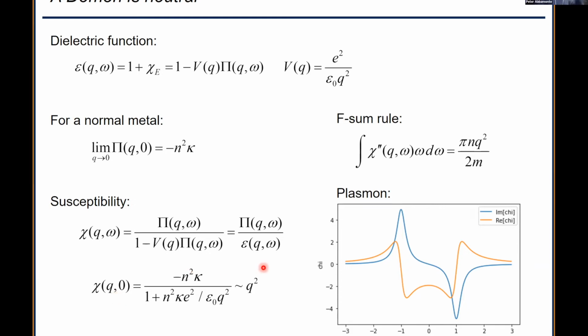What you see if you just do a measurement is there's a plasmon at finite frequency that's determined by the square root of 4 pi N e squared over m star. And if you do the f-sum rule, the spectral weight in that thing is required by the f-sum rule to go like Q squared. The consequence, then, that matches up with this pi, is that it forces the thing to be a metal. I'm being a little bit mechanical because I'm not a theorist. But this is what happens in a metal. So the compressibility sum rule and the finite conductivity and the plasma frequency and the f-sum rule all sort of work together in a way that makes sense.